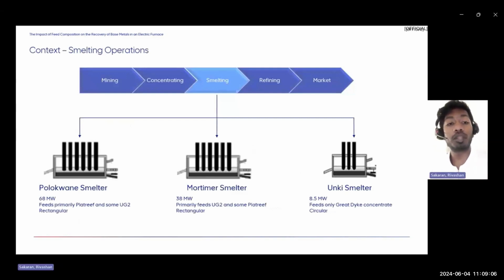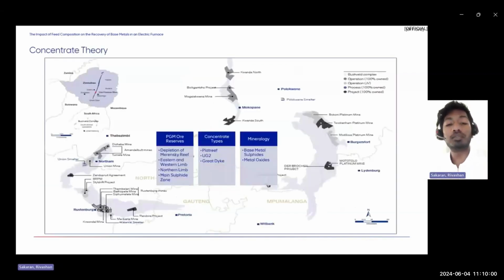Now, in the context of Anglo American Platinum, when the work was done, we primarily looked at three smelters: the Polokwane smelter, Mortimer smelter, and Unki smelter. What is key to note is the differences between these smelters. All of these smelters operate at different megawatt ratings, with Polokwane the largest at 68 and Unki the smallest at 8.5. It is also worth noting that Unki is circular, whereas the Polokwane and Mortimer smelters are rectangular in shape. Also, the type of feed is very different, with Polokwane feeding primarily Platreef ore, Mortimer primarily UG2, and Unki primarily feeding concentrate obtained from the Unki concentrator in the Great Dyke. And so why is this important to note?